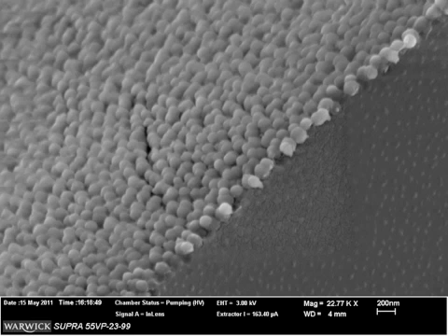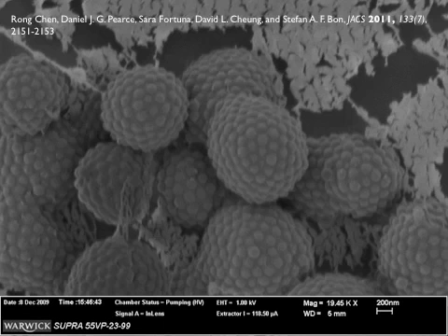There's a gold finger on top, but obviously if you hit this with the electron beam, ice will start to sublime and it recondenses here. So if you wait longer, you see these little things go. If you're not sure whether that's a particle or an artifact, you just zoom in with the electron beam, and if it disappears, it was an artifact. So it's a bit fiddly, but you can make really nice pictures.